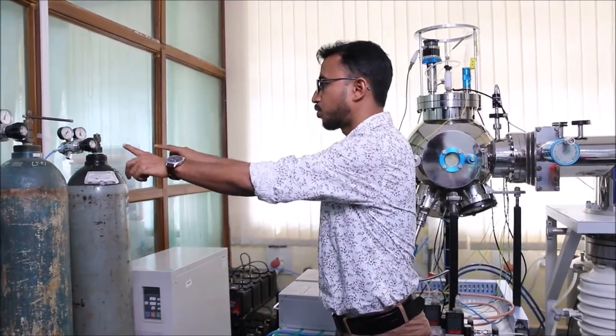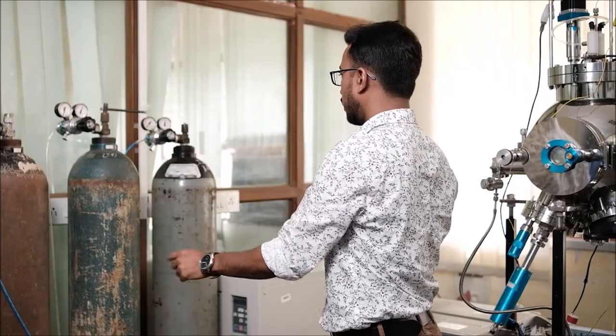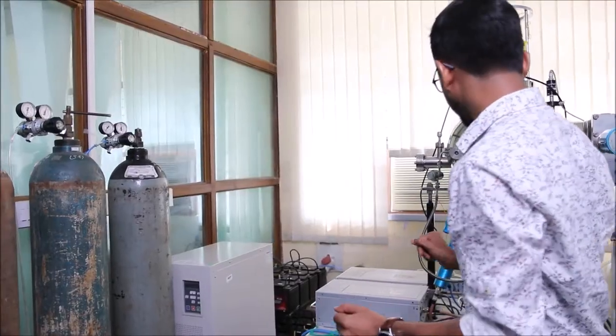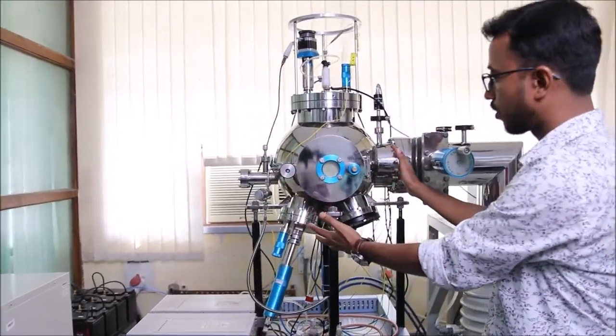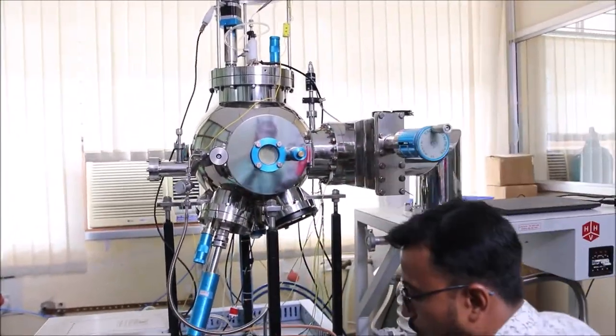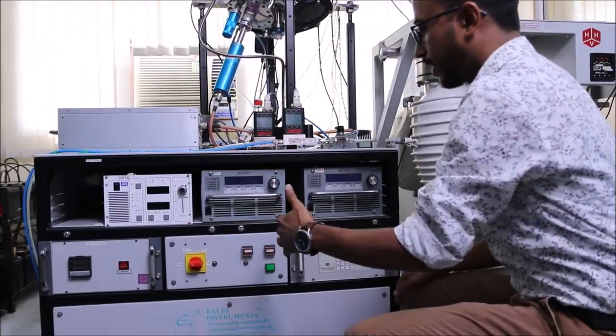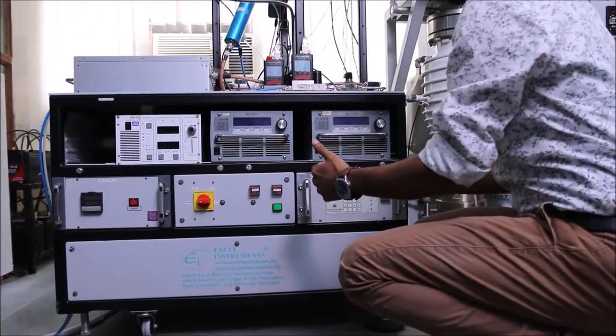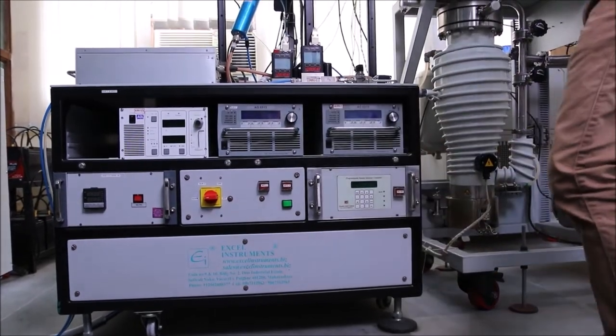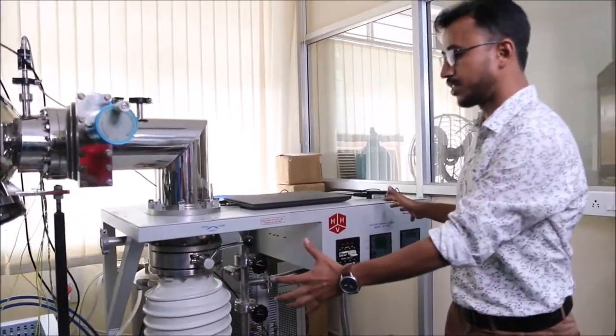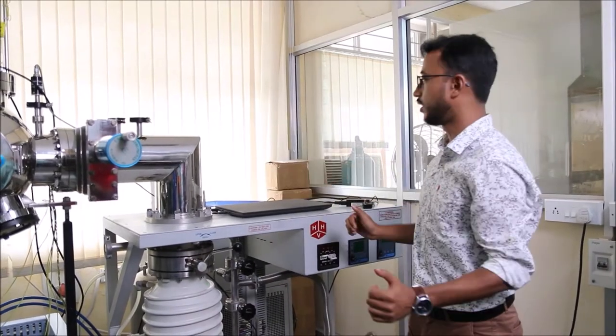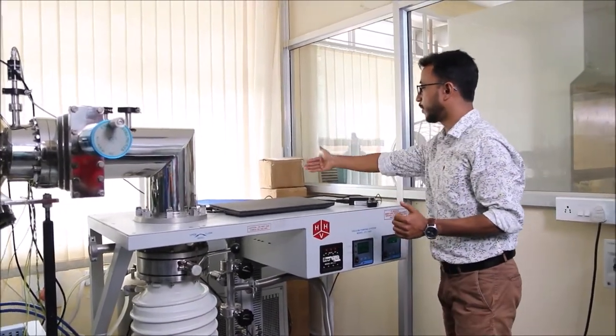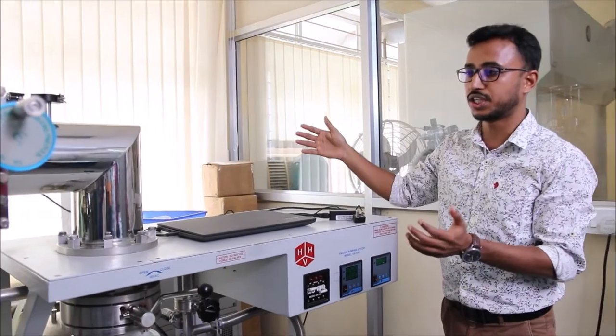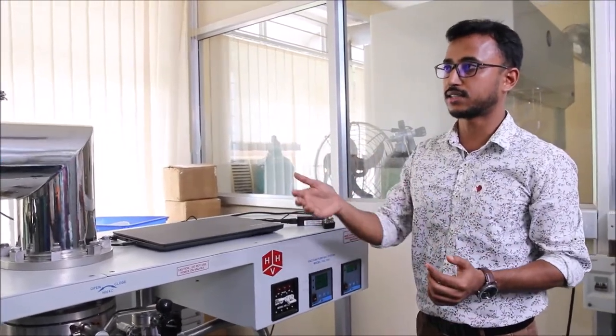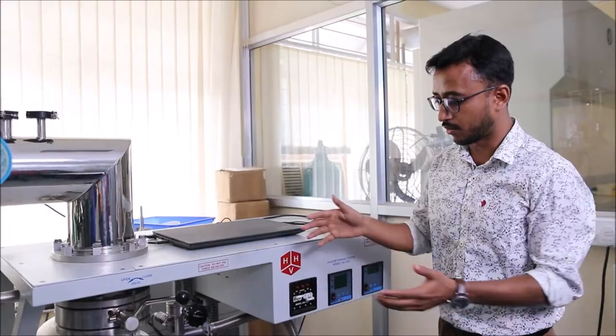So broadly, there is the gas unit part, which consists of the three gases, argon, oxygen and nitrogen. And then this is our sputter system, where the actual deposition occurs. This is the controlling unit, where the power, temperature and also the rotation controller unit is there. And then next comes the vacuum system, which is responsible for evacuating the chamber. And on the back of it, we have a chiller unit which supplies the chilled water to the guns and to the substrate holder and also to our vacuum unit system.